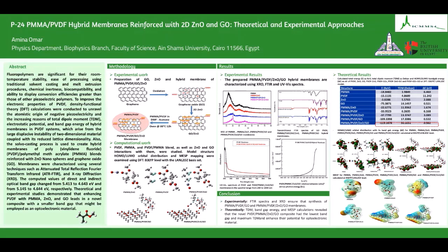The experimental work focuses on the preparation of the graphene oxide with zinc oxide and the hybrid membrane and the composite membrane between polymethyl methacrylate and PVDF and graphene oxide and zinc oxide. And the computational work was also done by density functional theory to have the mapping of electrostatic potential and HOMO-LUMO orbital distribution. From the experimental results, we focus on XRD and FTIR and UV-visible to have the band gap.